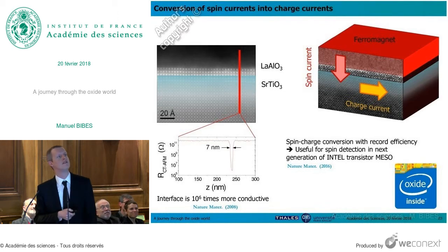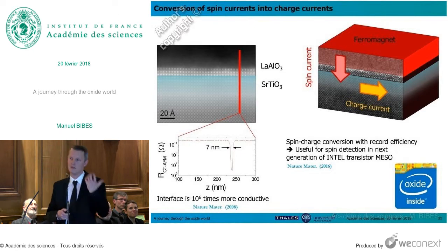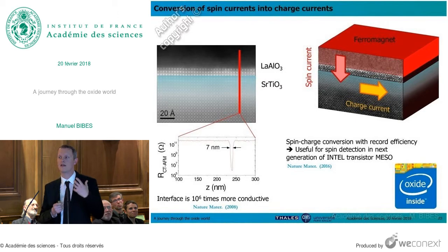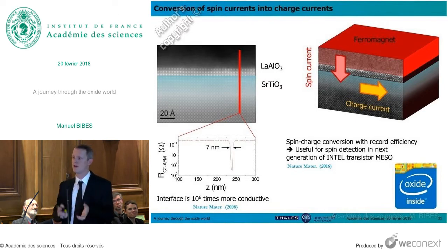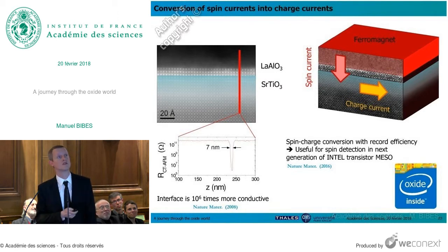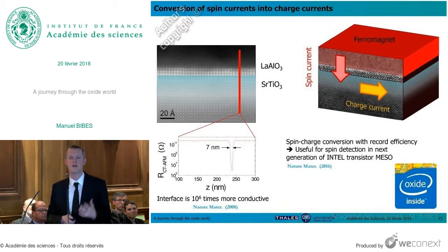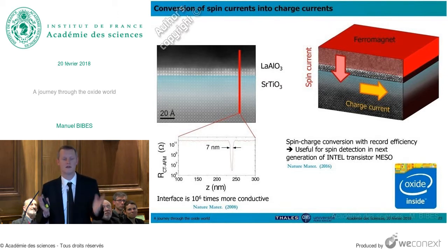And we investigated those materials for a few years. We demonstrated that they have this very low resistance just at the interface. And now we are combining them with ferromagnetic materials because we have discovered that they can very efficiently convert a spin current, so current of spins, into a charge current. So they are very efficient to read, if you want, the magnetic information. So efficient that the company Intel is very interested in these results for the new transistor that they have proposed to replace the conventional so-called CMOS transistor, which we have now in all our phones and computers. And so now you have this logo on your computer, but maybe in a few years we have this one. That's what we hope, actually.